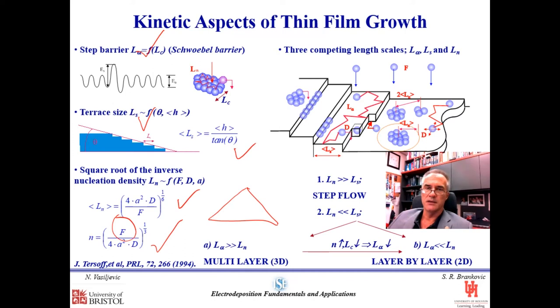We sometimes try to achieve 2D growth by manipulating the growth conditions, or conditions for electrodeposition, in order to force systems that naturally grow in 3D to grow in 2D mode. This is typically achieved by increasing the nucleation density, or basically increasing the flux, and mitigating the strength of the Schwoebel barrier, and basically the length scale L sub alpha. I will address more details on how we do this in electrodeposition in the following slides.